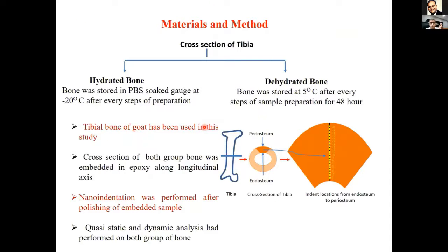So we tried to see how this plays a significant role. What we have done is, we have taken the hydrated bone, stored in the phosphate-soaked gauze, and at -20 degrees centigrade at every step of preparation. And the dehydrated bone we have not placed in the soaked gauze, but we have stored at 5 degrees at every step for 48 hours.